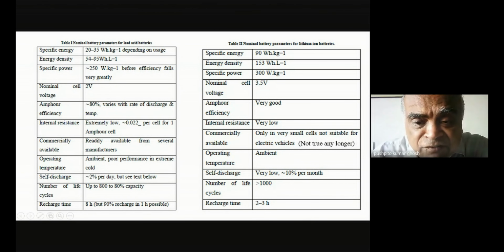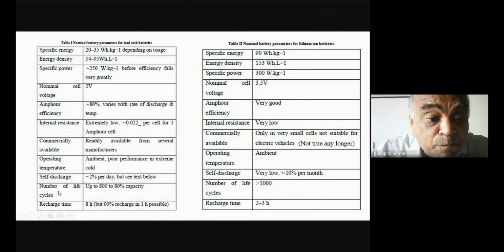The self discharge, you remember that if you are not using your battery, what will happen? Over here in the lead-acid battery, every day you lose about 2%. So if you come back after a month or a month and a half, there's nothing, your battery is dead. Over here, it is as low as 10% in a month. So even if you come back after 2 months, chances are that your battery will be running. The number of life cycles, how many times can you charge and discharge, it's somewhat better with the lithium-ion battery, greater than 1,000.